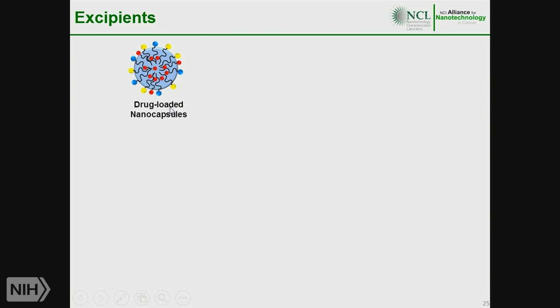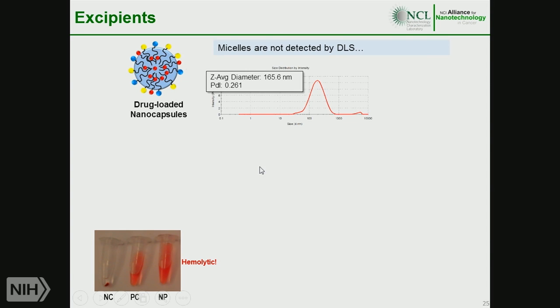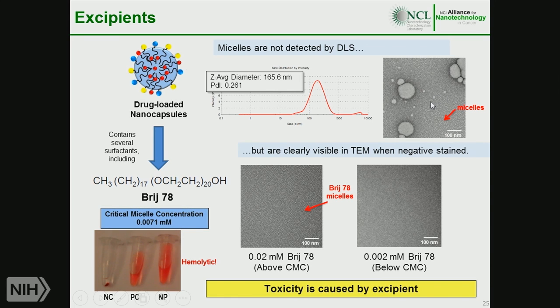In this case, we are using drug-loaded nanocapsules, and then this material was studied in the biological assays and hematology assays. We observed that this material was hemolytic. Why are these nanoparticles hemolytic? The physicochemical characterization, again, we are using dynamic light scattering, did not show any small peaks. It shows that average particle size is 165 nanometers, which was expected, but transmission electron microscopy with negative staining shows presence of the small micelles.